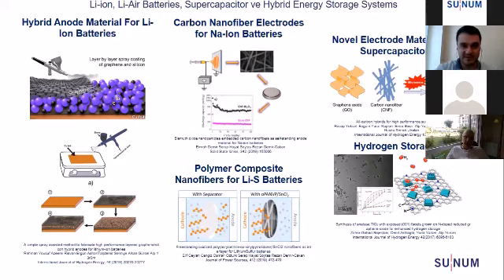And then on the other side, you can see carbon nanofiber composite electrodes were prepared for sodium-ion batteries, combining bismuth oxide and carbon nanofiber. The electrospinning method was used with that system. Three times higher discharge capacities were obtained when compared with conventional carbon nanofiber electrodes. And on the other side, polymer composites and nanofibers were produced to use in lithium sulfur batteries as electrolyte stabilizer. And very successful results were also obtained with that system.